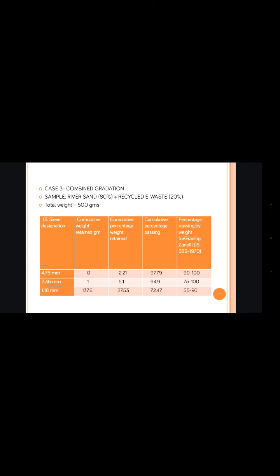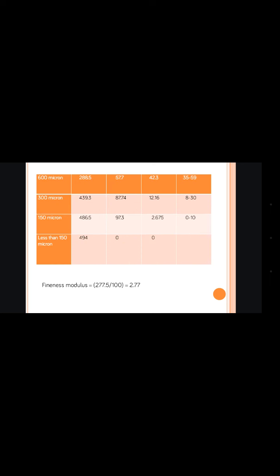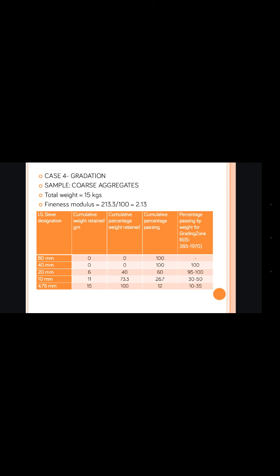The reason why we took 20% recycled e-waste is that 20% is the maximum percentage of e-waste we are about to incorporate in the concrete. So if the sieve analysis for that percentage is taken, it's more than enough. The combined gradation is about 2.77. And in case 4, coarse aggregates, the fineness modulus obtained was 2.13.